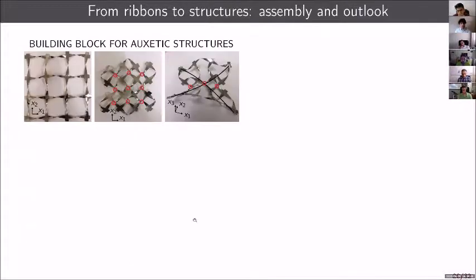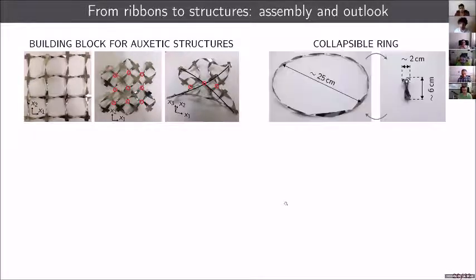Now, with this idea in mind, we tried to show some potential for creating morphing structures with the systems. Here, we wanted to create an auxetic structure, so with negative Poisson's ratio, for now just in plane. So we managed to create it, and here, these red dots correspond to points where we put some tape in order to keep the joints together and show what the deformed pattern looks like. And you can see that it does have negative Poisson's ratio. Now, the cool thing is that if you remove some of these joints, you have an out-of-plane bending of the overall structure, which we think is something quite interesting.